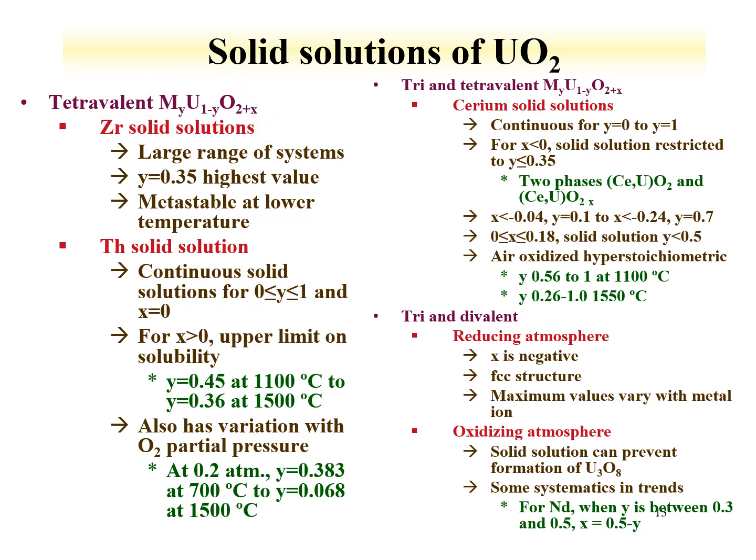Unlike the zirconium, thorium, which has an ionic radius very similar to uranium, they're both about 1 angstrom, where zirconium is about 0.72 angstrom, so it's much smaller. Thorium makes a solid solution with uranium over the entire range.